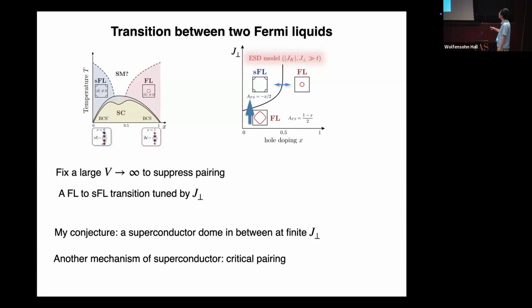So we ask, what is the transition between these two Fermi liquids? The Fermi surface volume dropped by 1/2. Okay, so it's definitely beyond the Landau-Ginzburg, for sure. So one way to study this transition is, you fix the large J-perp and you change the doping. But I want to focus on another regime. Our V is super large, repulsive to infinite. The pair is suppressed deep inside these two Fermi liquids.